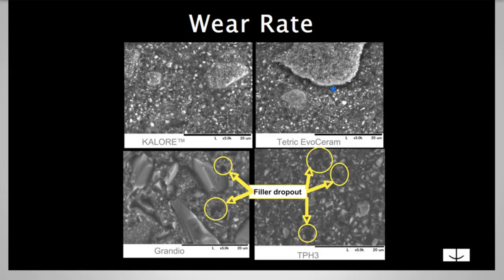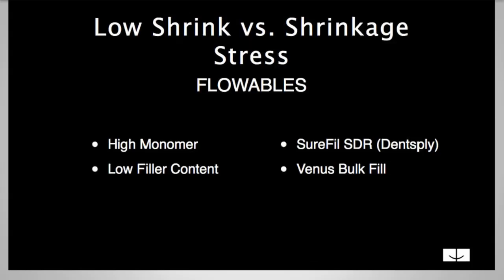So we have multiple flowables that have been identified as bulk fill with low shrinkage stress. Now the ones that have really changed the market would be SureFil SDR Flow, and that has some pretty high shrinkage but really low shrinkage stress. So they've done things in there that are really decreasing shrinkage stress. So if you're going to use a bulk fill flowable composite, I would definitely recommend SureFil SDR Flow. Venus Bulk Fill has also changed some things, which has allowed them to do it. But I would say if you're going to choose a flowable for bulk fill, then SureFil SDR Flow.